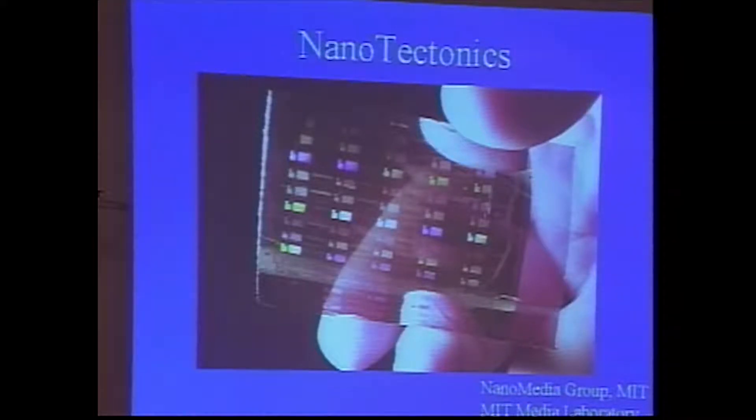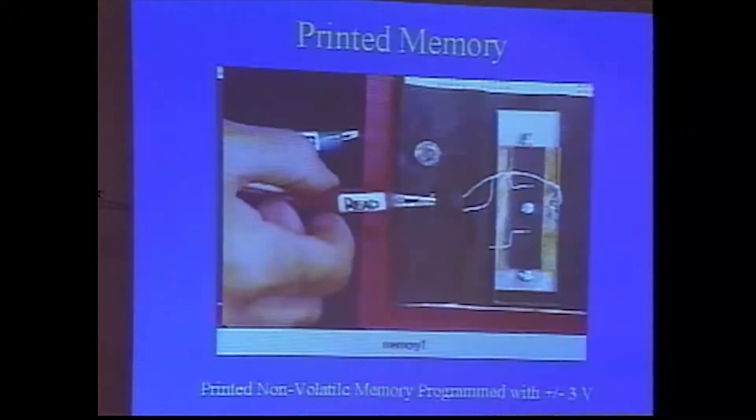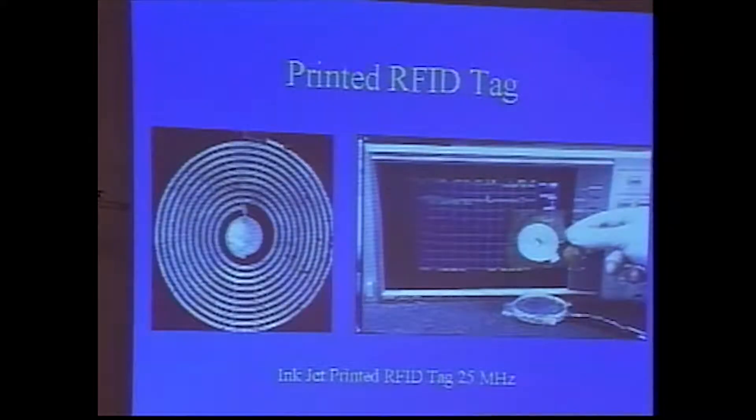One very important aspect is our ability to print multi-layer structures, the self-planarization property of this chemistry. We've actually printed, using some other technology, a very large number of layers. In fact, as many as 400 layers or so. Vacuum deposition of a material like silicon is conformal. It drapes over every structure you have. This technology, this chemistry, is self-planarizing to a very good degree.